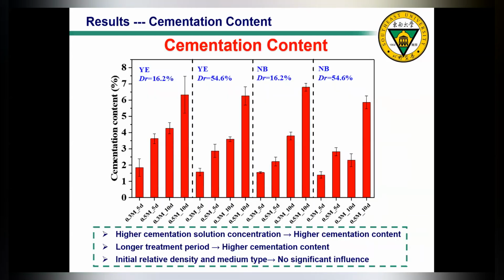Firstly, let's see the cementation content results. Here there are several columns, divided into 4 boxes. Within each box, from left to right, the cementation content increases, because either the cementation solution concentration increases or the treatment period increases. So we can conclude that higher cementation solution concentration as well as longer treatment period could lead to higher cementation content. This is true for all 4 cases with different enrichment media and relative density. Meanwhile, if we compare these 4 boxes, the initial relative density and the medium type do not significantly influence the cementation content level.